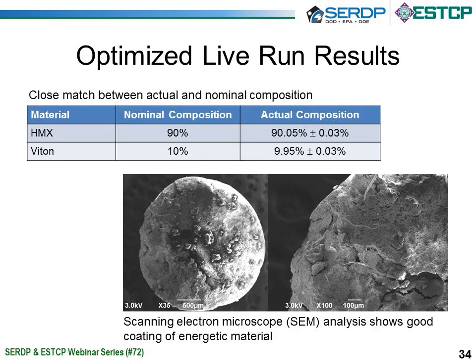So we took a sample of this optimized run, and we ran it for compositional analysis. Again, the nominal composition was 90% HMX, 10% Viton, and the actual composition came out almost spot on with 90.05% HMX and 9.95% Viton. So you can see we had an extremely close match between the actual and the nominal composition. We did some scanning electron microscopy of the materials, and it shows very good coating of the energetic material with the Viton thermoplastic material. Slide 35, please.